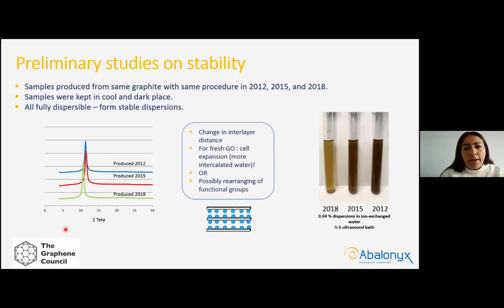So we took an XRD, and here we have it. We can see some change in the interlayer distance due to what we suspect is possibly a rearrangement of the functional groups. And actually, there are studies that suggest that these changes happen between 30 and 40 days after the material has been produced. And that one of the main changes that happens in the material is that the epoxide on the surface starts to interact with adjacent hydrogen from the material itself or from the atmosphere, and to form water molecules. These water molecules can be intercalated between the sheets, and that is one of the hypotheses of why we have this change in the interlayer distance. So of course, we need further research on this.